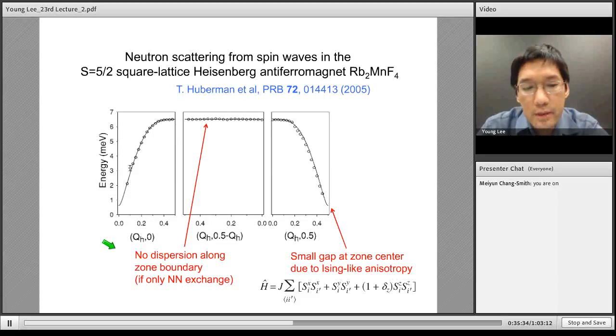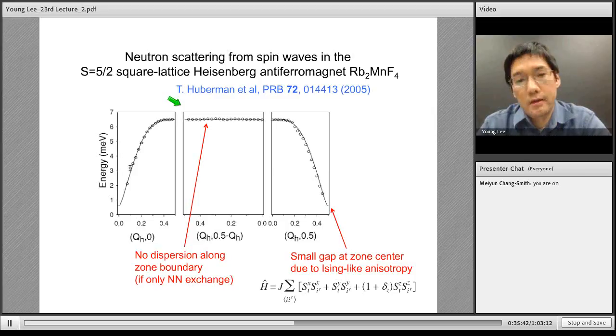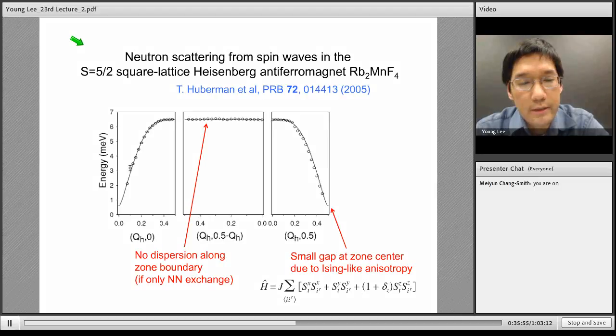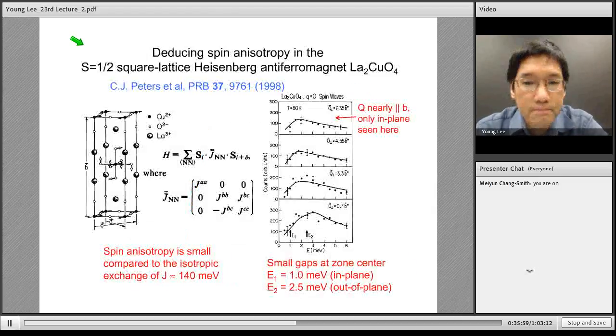But something that's quite nice from the linear spin wave theory calculation for just nearest neighbor exchange is that it predicts there to be no dispersion along the zone boundary, and that is what is seen here. So this linear spin wave calculation for this relatively large spin square lattice antiferromagnet seems to work quite nicely.